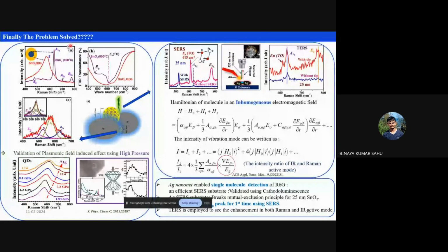But thanks to this problem, basically because of that we could enter the field of plasmonics. But here, plasmonics doesn't stop surprising us. And here I will not explain it much, because again it will be too much. As an extension of this work, we also did some TERS. This is known as tip enhanced Raman spectroscopy. In that, generally we use the AFM tip, and we collect the spectra.